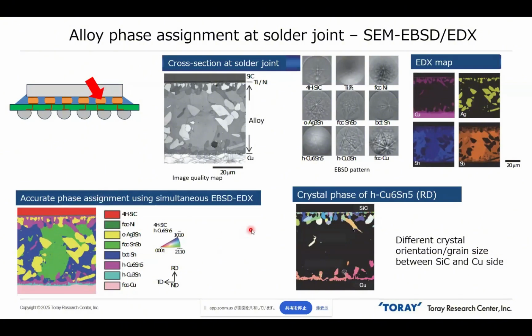Then we can also get the crystal orientation map of one phase. Even in this case, this sample has a bump thickness of 50 or 60 micrometer order. So in this case, SEM-based EBSD and EDX with a spatial resolution of micrometer order is very useful.